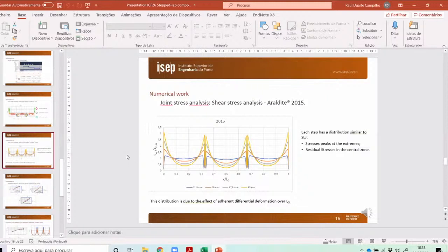They highly increase with the overlap length. This is for a different adhesive, but the concept is the same. So as we increase the overlap length, the stresses go from the blue line to the yellow line. And since this adhesive is very brittle, for high overlap lengths, the adhesive cannot undergo plasticization at these peak stresses, and then the joint fails prematurely.